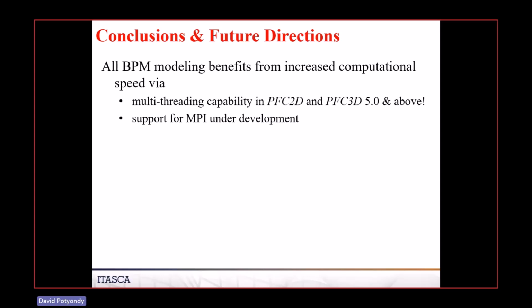And so the guys at BP are running that XSite on these hydraulic fracturing problems. BP has some enormous giant compute nodes where they have hundreds of machines, and that's working very well. They're getting speed ups of, I think, on the order of 20 or 40, and they're building extremely large models. But that took a huge amount of time and funding to do, and that was much easier to do because it's a fixed lattice of springs. Once you know that fixed lattice topology, you can, in a reasonable way, pass that off to these different processors and make that work.